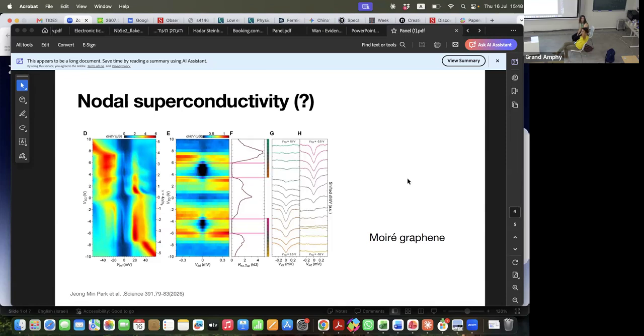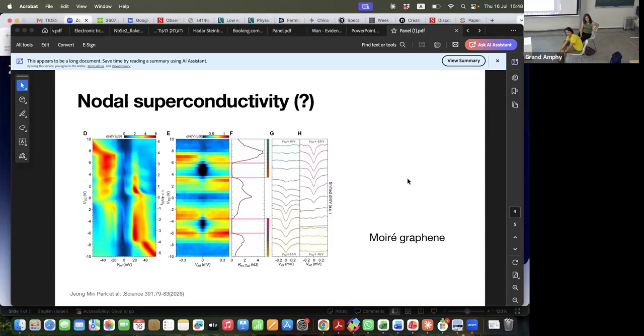Miguel, you wanted to say, do you have a comment? Yeah, I want to make a comment. There are many STM, STS papers claiming nodal superconductivity based on the V shape of the superconducting gap. But my feeling, and I'm going to say something that is not politically correct, is that the literature is full of papers claiming this where nobody takes care of the electronic resolution of the system. Especially if you're dealing with gaps that are like 0.2, 0.3 milli-electron volts, you have to be super careful because radio frequency goes into your cryostat and broadens a lot, and then probably closes the gap.